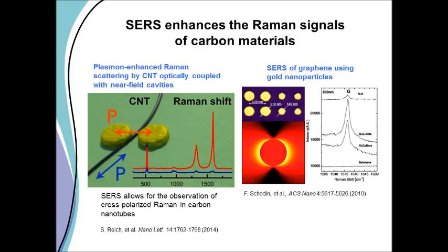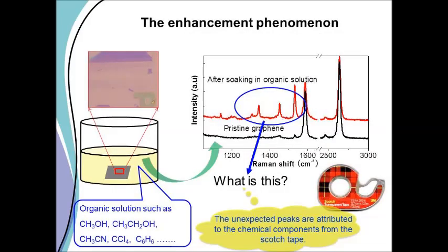One of the visitors coming to me, her name is Shi Lin, and what she did, she put a piece of graphene, and it had some Scotch tape on it. You know, when you make a sample, you take it off graphite, and then you make a single sheet, and not all the contaminant was removed. We heard about contaminants earlier today from one of the speakers. The contaminants were very important in this experiment because the contaminants are seen over here. So pristine graphene will have a Raman spectrum that looks like this. But if you don't take off the Scotch tape carefully, clean it, you get all these other peaks. So that was very interesting.